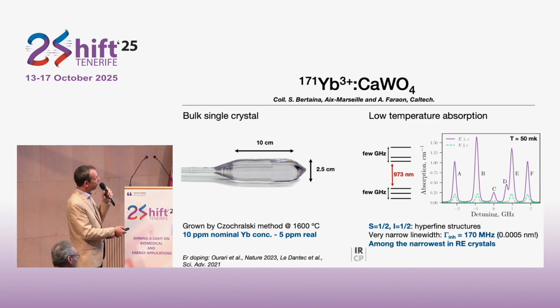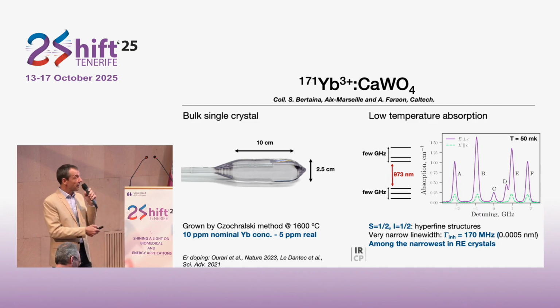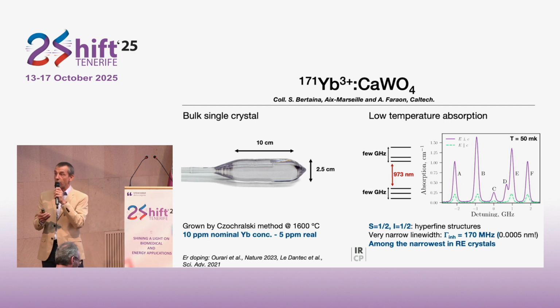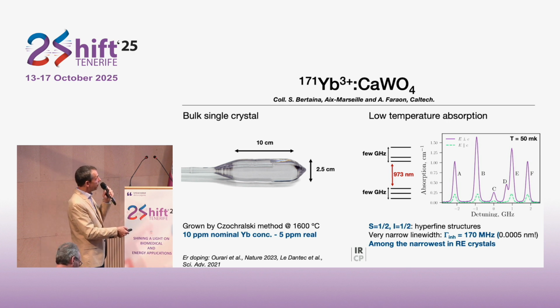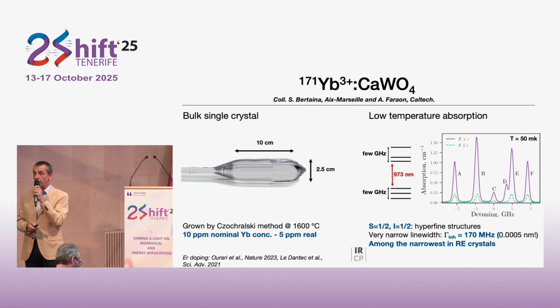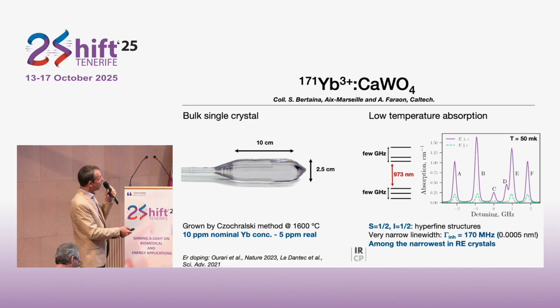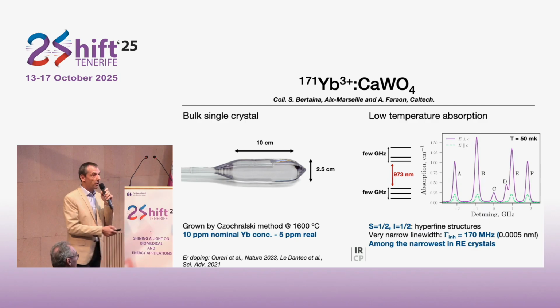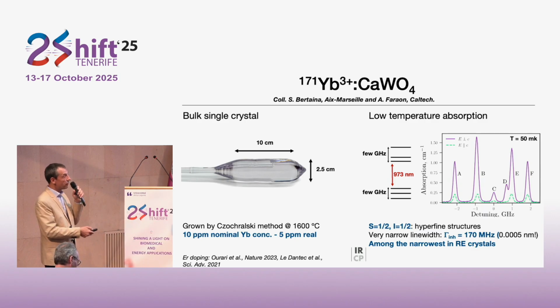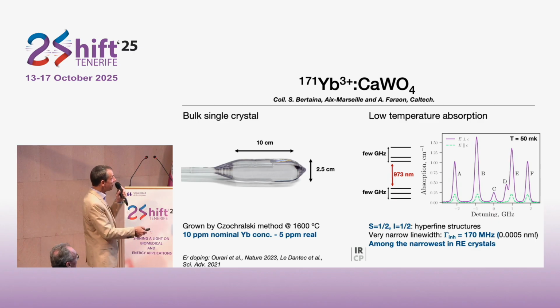So you notice that we have different lines here. This is due to the doping with ytterbium-171. This particular isotope of ytterbium has electron spin of 1/2. This is simply because ytterbium is a paramagnetic ion, but you also have a nuclear spin of 1/2. And the interactions between this electron spin and the nuclear spin will cause this lifting of degeneracies, and so you end up with 3 levels in the ground state and 3 levels in the excited state. And this is why we see these different transitions in absorption.